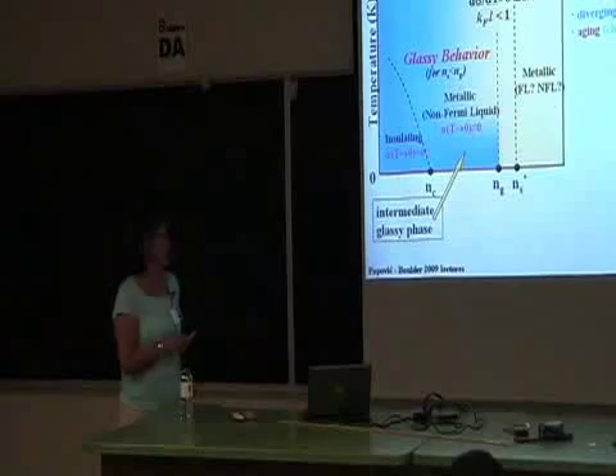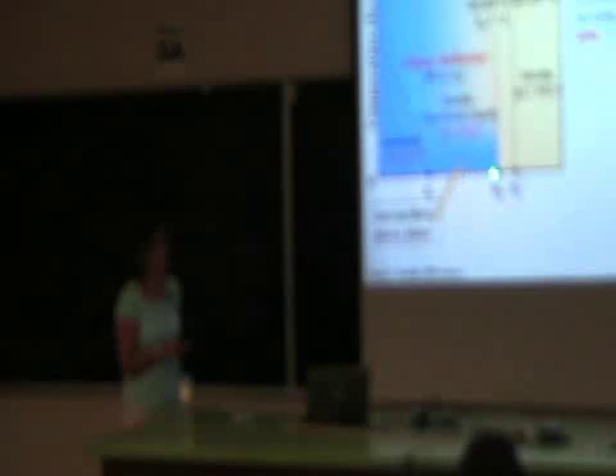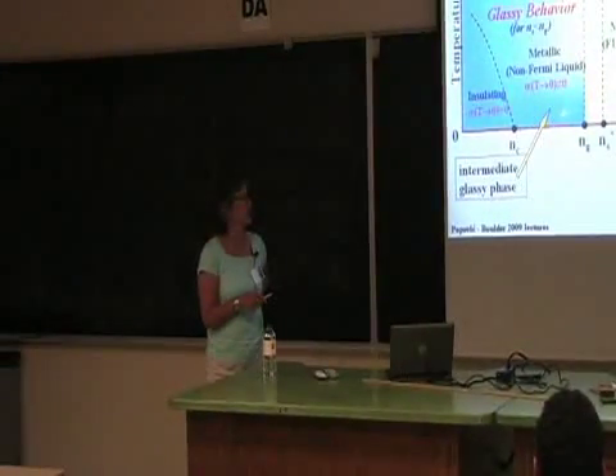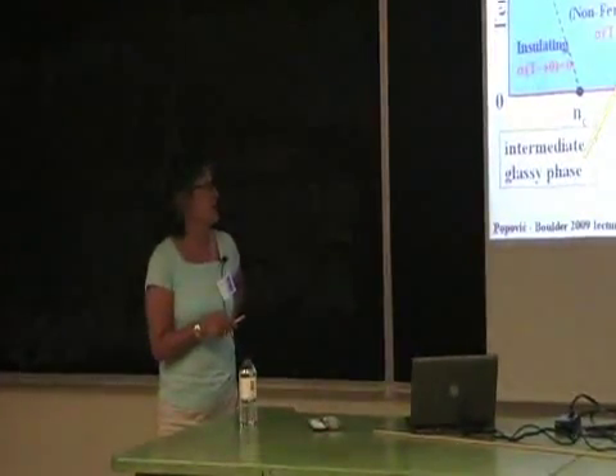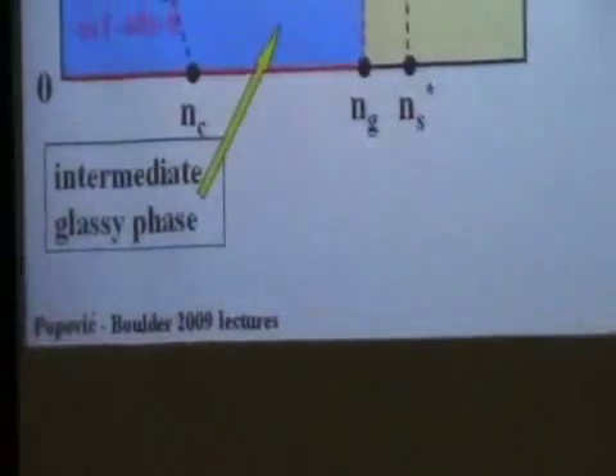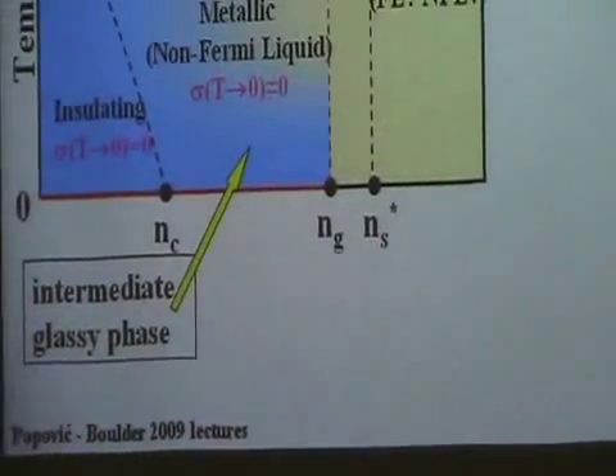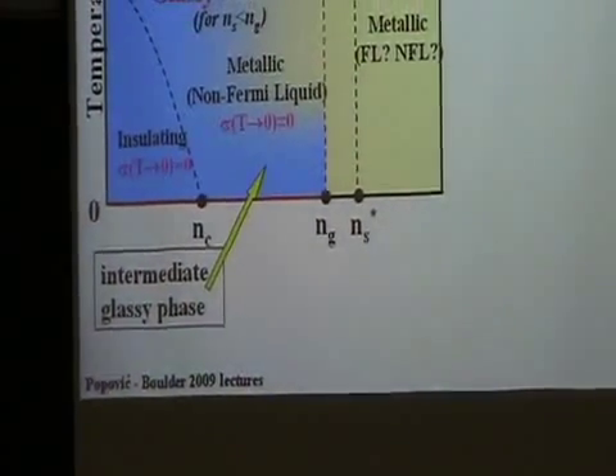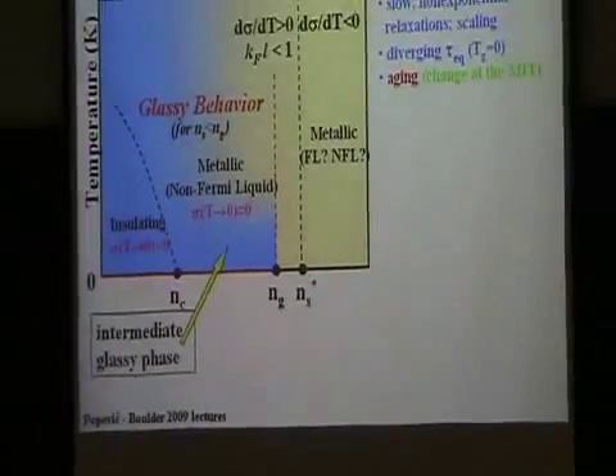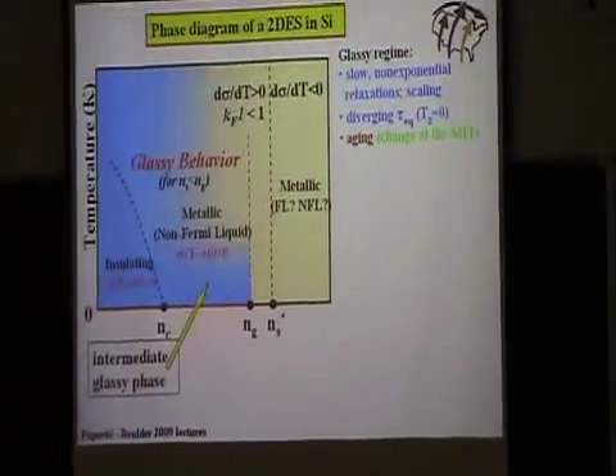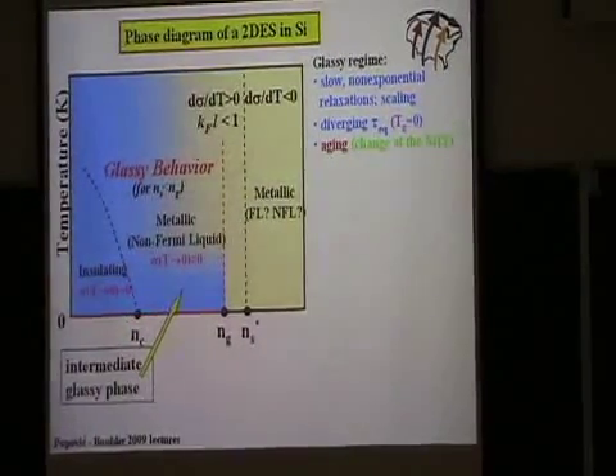What I discussed yesterday, so basically we established that there is a glass transition in a two-dimensional electron system in silicon at zero temperature for all densities below some density Ng, which is on the metallic side of the metal-insulator transition. In other words, we show that here in this system, an intermediate glassy phase emerges, which is also metallic with some kind of a strange temperature dependence. So the glassiness was established by finding non-exponential relaxations, scaling, diverging equilibration time in the zero temperature limits, and we also looked at aging and found that the aging properties change at the metal-insulator transition.